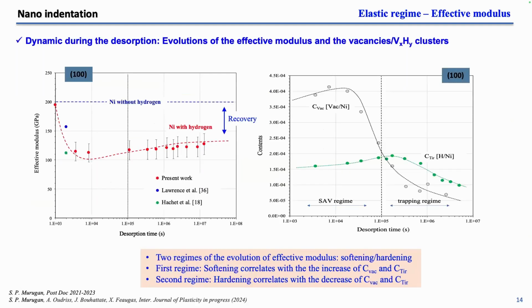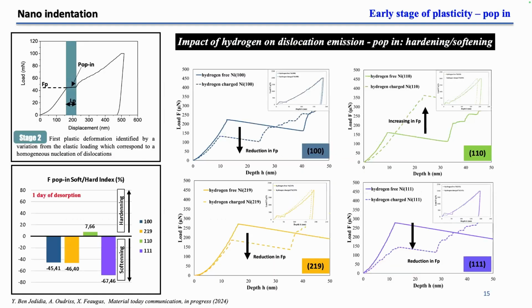Now, during the desorption, we show a specific decrease of the effective modulus, but we have a progressive recovery, though not a complete recovery, because the concentration of vacancy is not completely recovered during the desorption of hydrogen. Now, for the popping, it is characterized by a load and a length.